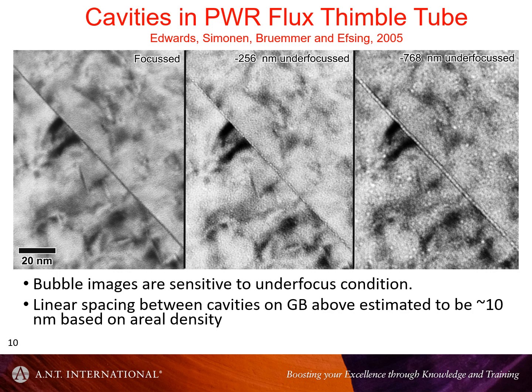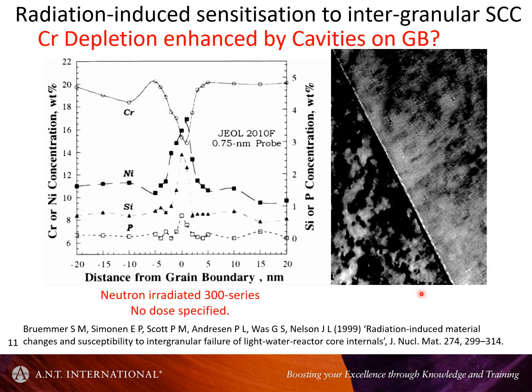when you look at that, and then you look at other past observations, in this case, this is some work by Steve Bruemmer, and you look at the images that went with chromium depletion at grain boundaries, you have to be scratching your head and say, well, what is this? It almost looks like you have a string of helium bubbles, just like the Danny Edwards case, along the boundary. Doesn't look right. It looks like it's shifted somewhat, and the contrast is peculiar. But again, if you're familiar with electron microscopes, shifts in images depending on the height and stuff like that, that's okay. You expect that, and the thing to do is to align the microscope well.